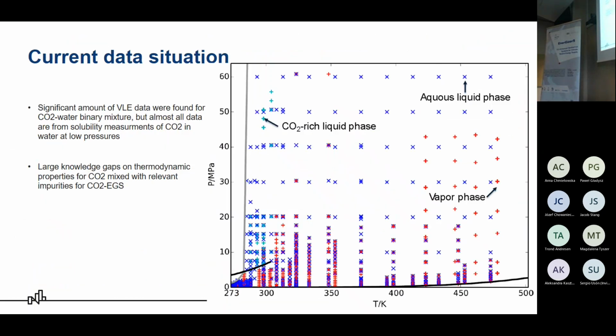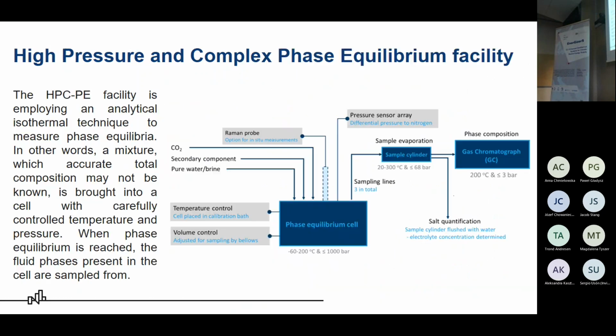What is the current data situation? A significant amount of early data was found for the CO2 and water binary mixture, but almost all data are from solubility measurements of CO2 in water at low pressures. And we want to measure the VLE at higher pressures, up to 100 megapascals. And we want to have bigger density in this area, but also in this area higher than 60 megapascals. So there are some large knowledge gaps of thermodynamic properties for CO2 and relevant impurities for CO2-EGS systems.